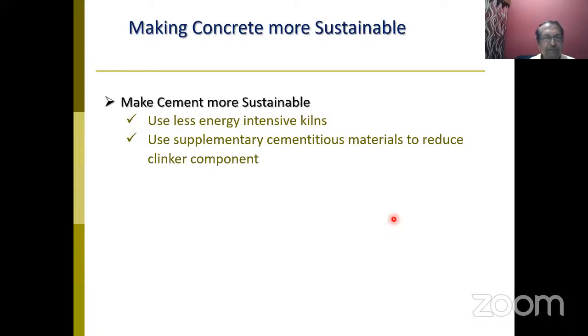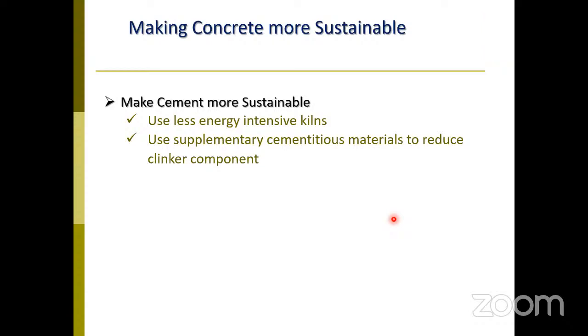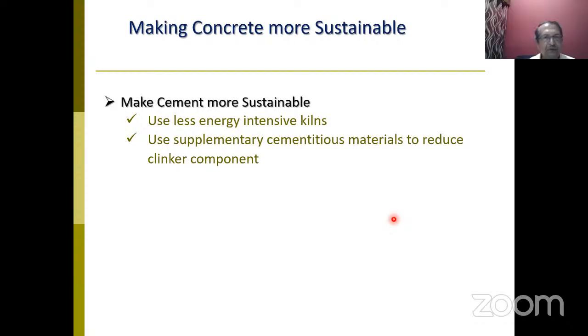sometimes more than even 50% of alternate materials in the cement, which is called blended cement. So for example, if you use fly ash, up to 35% of the 1 ton of cement happens to be fly ash, which is not contributing to carbon dioxide emission. Or if you are using slag, GGBS, which will be probably upwards of 50% of the volume of cement. And in fact this also enhances the quality of concrete and contributes to sustainability.